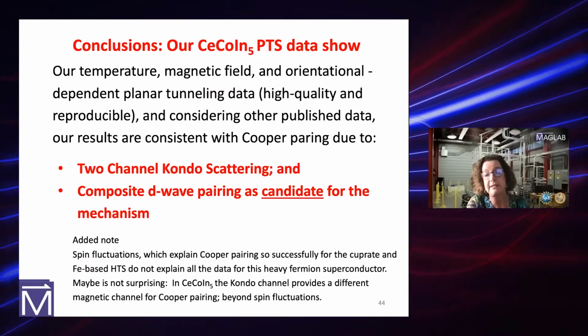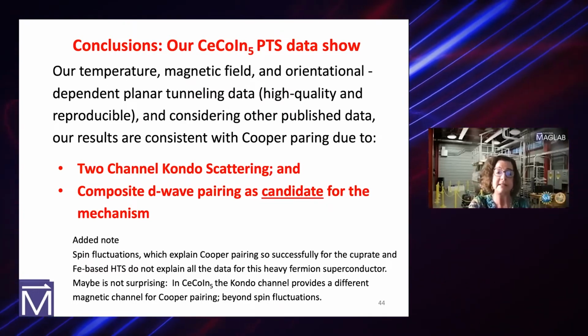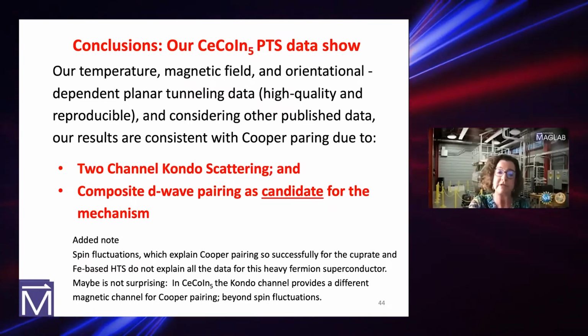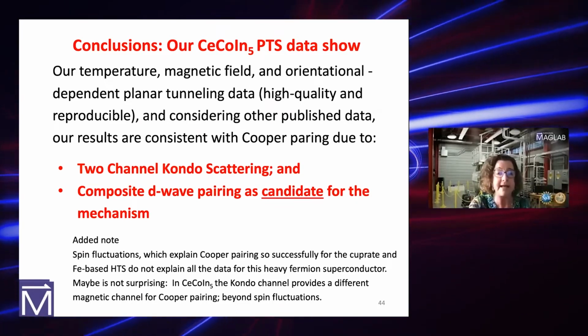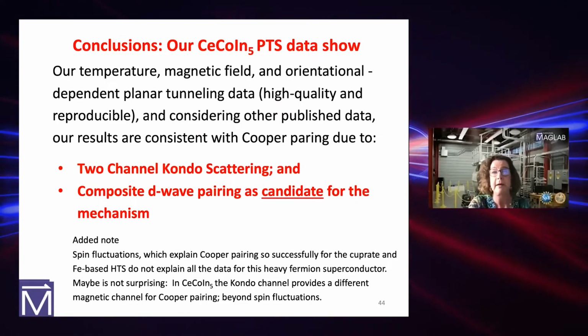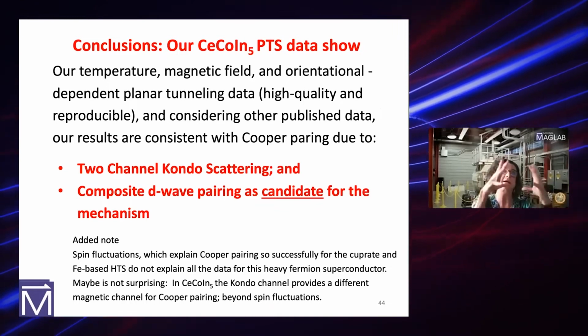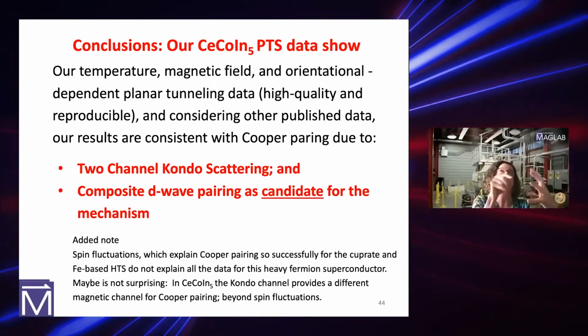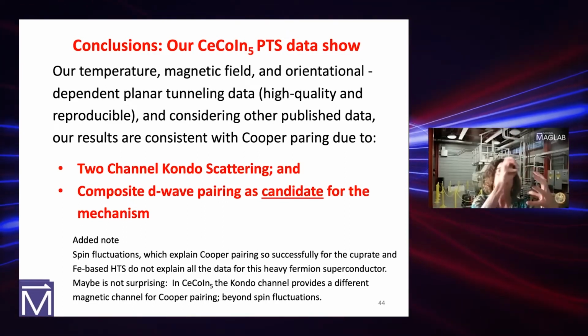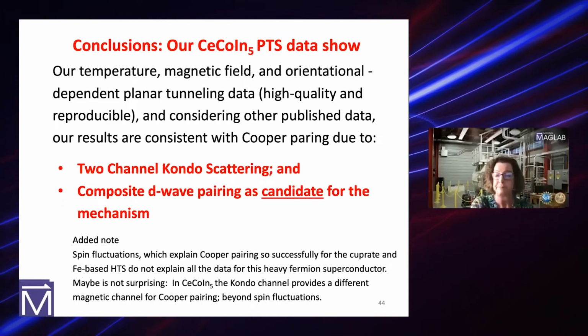And that's just repeating it, and there's some data that we plotted up, and it gives you the peak position, et cetera. So our conclusion, which I can discuss in more detail, and we can argue because I've been doing Kondo scattering and tunneling for years, but this really looks like a 2-channel Kondo scattering. And a candidate is a composite d-wave pairing, but definitely it looks like a bulk example of what has been seen in tunneling before, which is 2-channel Kondo scattering in an interface. We believe we're seeing it in the bulk.